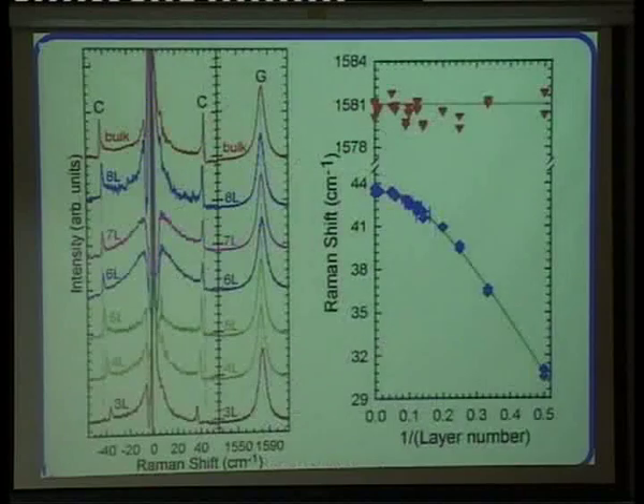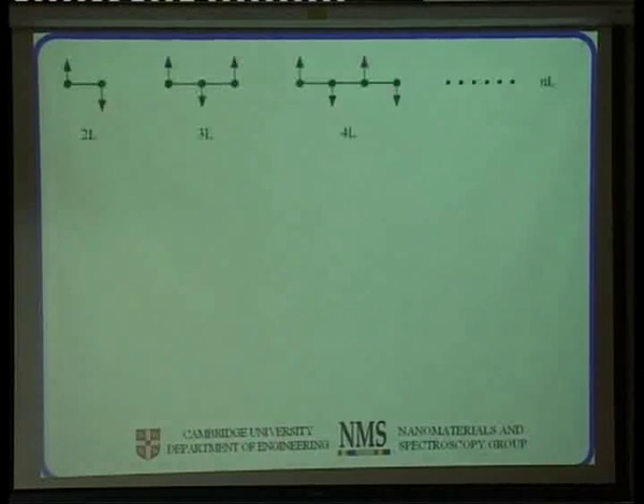And you can also fit all the data, and I want to show the fit here. This is the G peak position with some scatter, and that's the C peak position, and the scale is essentially the same. So there are about 16 cm^-1 between here and there, and about 16 between here and there. And there is a massive change in the C peak, while the G peak doesn't change at all with the number of layers. Yet again, because the G peak fundamentally is totally in plane and doesn't care about the layer number. So in this way, we can actually monitor directly the change of peak position with the number of layers. And the interpretation of this behavior is actually quite simple.